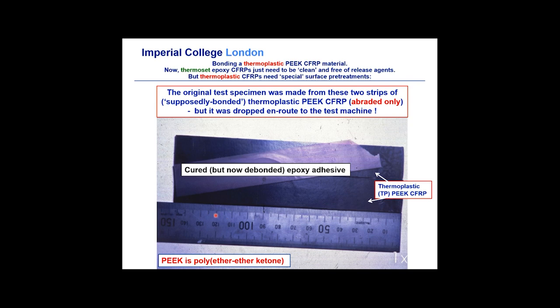To give an example of this, some work we did a little while ago was on bonding of thermoplastic composites. The thermoplastic composites we looked at were based upon polyether ether ketone as the matrix, PEEK, a high performance matrix widely used in aerospace. So we've got a thermoplastic PEEK CFRP. Now, if we had an epoxy CFRP, which is a more conventional type of CFRP, these surfaces just need to be clean and free of release agents. But thermoplastic CFRPs need special surface treatments.